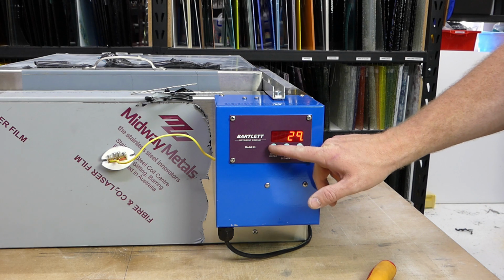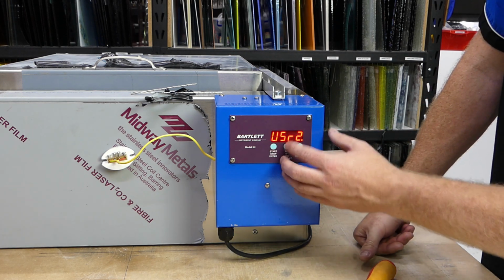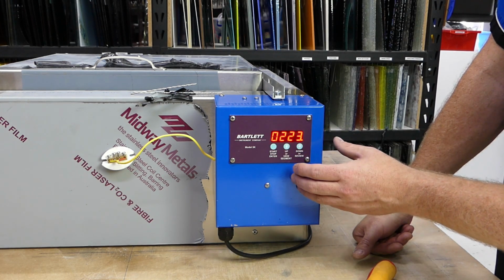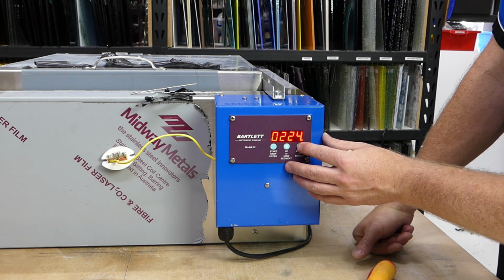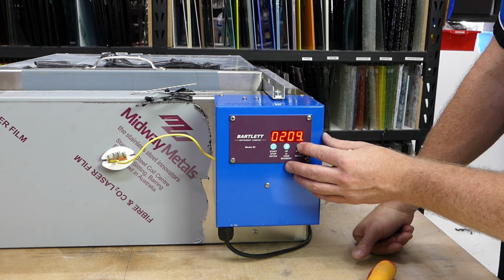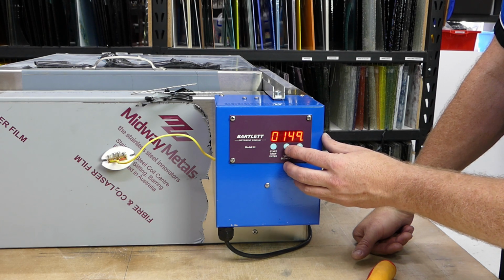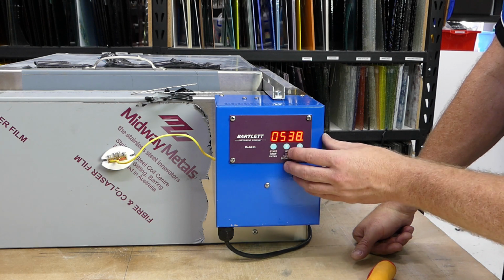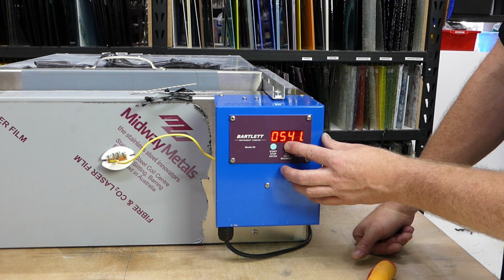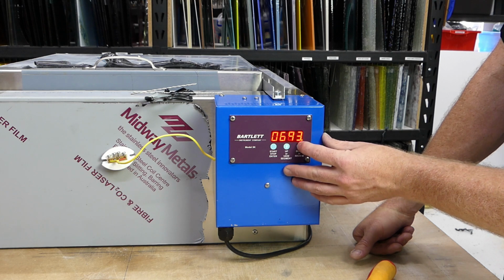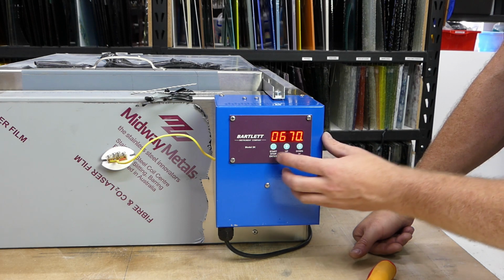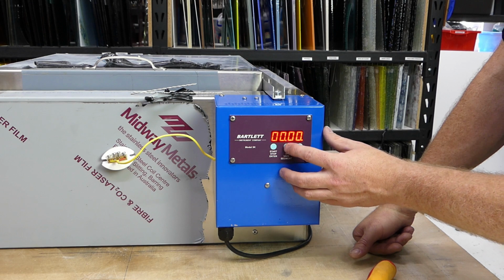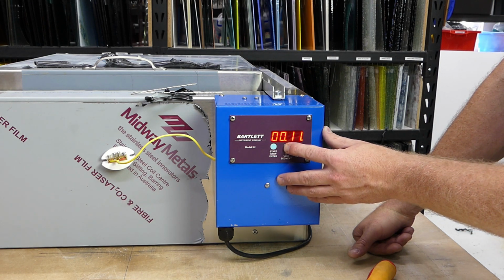So with segment number 3, so user number 3, we're just going to do a slump. This one's a 5 segment slump. Our first ramp is at 150 an hour. We're going to go up to 670 degrees. Sometimes the controller is a little bit finicky. And we're going to hold it there for 30 minutes, just to let the piece equalise in temperature completely.